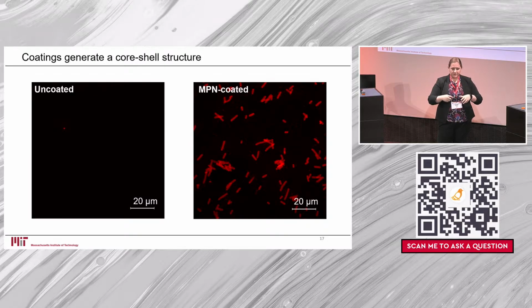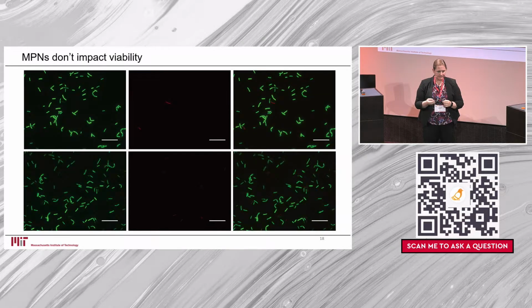And our coatings form this really unique core-shell structure. So we can stain the coatings with a fluorescent molecule. So we have uncoated cells, we obviously don't see anything. But on the coated cells, what you'll see is darker red around the edge and lighter in the middle, indicating that they're actually forming all the way around the cell.